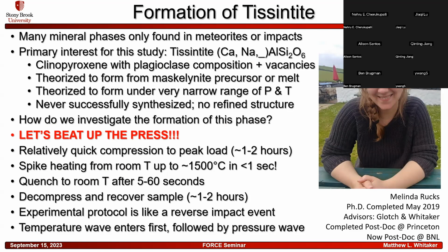So we did relatively quick compression to its peak load. And then once it was at its load, we did a spike heating protocol where we took it from room temperature up to about 1500 degrees Celsius in less than a second. And we then would quench to room temperature, depending on the experiment, after 5 to 60 seconds. And we were able to monitor all of this with X-ray diffraction as it was going on. We could decompress and recover the sample. And basically, this experimental protocol is very much like a reverse impact event.